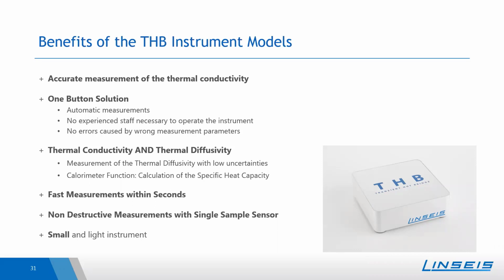Advantages is also that the thermal conductivity and the thermal diffusivity can be determined, and because of that, one can also calculate then the specific heat capacity. The measurement is very fast. As you have seen in the example of PMMA with a thermal conductivity of around 0.2 watt per meter Kelvin, it took like 20 to 30 seconds, one measurement, so it's very fast. And by using this single-sided sample sensor, one does not need to destroy the sample by cutting it into two halves. The instrument is very small and light, so it's a small tabletop instrument, which you can also carry around in a suitcase.